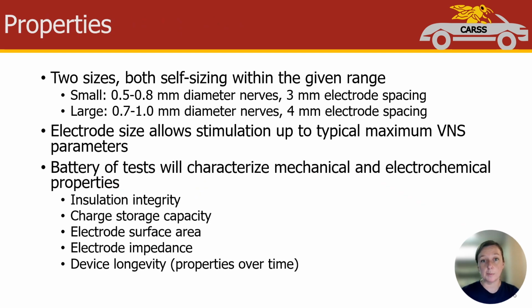The cuff electrode will come in two sizes, both of which will be self-sizing within their given ranges. The small cuff will fit nerves between 0.5 and 0.8 millimeters in diameter, with a 3 millimeter spacing between electrodes, and the large cuff will fit nerves between 0.7 and 1.0 millimeters in diameter, with a 4 millimeter electrode spacing.